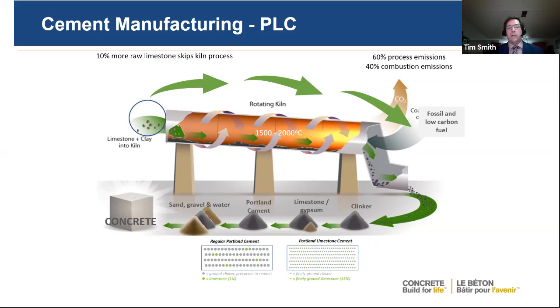But what we do is when we collect the clinker, instead of the gypsum and limestone, the limestone being at up to 5% for a general use cement, we go up to 15% in the Portland limestone cement. So that's an automatic around 10% reduction in amount of CO2 attached to the cement. So it's kind of a green for free. There's no additional cost to doing it.